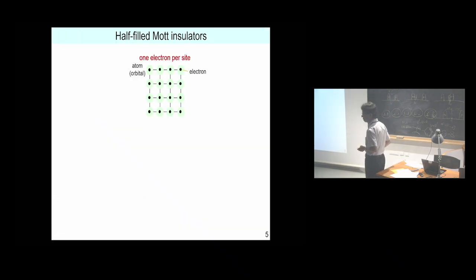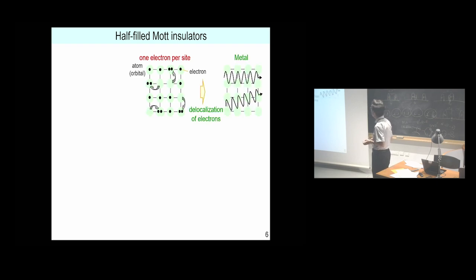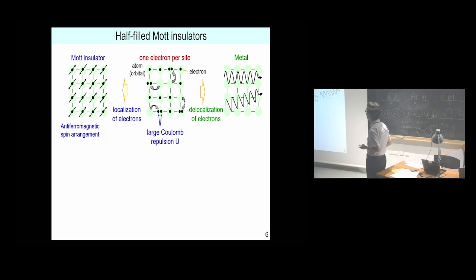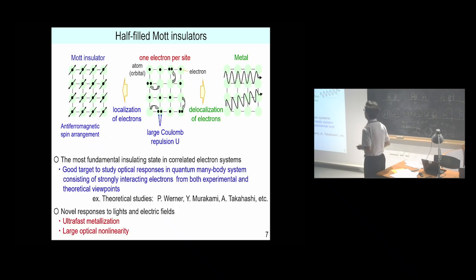Here, I will focus on half-filled Mott insulators, which have simpler electronic structures and are hardly affected by lattice degrees of freedom. This is a schematic of a system with one electron per site. Since two electrons can occupy each orbital, electrons are free to move around, and the system should be a metal. However, if a large on-site Coulomb repulsion works between two electrons on the same site, electrons are localized on each site, and the system becomes a Mott insulator. In this case, electron spins arrange antiferromagnetically like this. This half-filled Mott insulator is the most fundamentally insulating state in correlated electron systems, so it is a good target to study optical responses in quantum many-body systems consisting of strongly interacting electrons from both experimental and theoretical viewpoints.